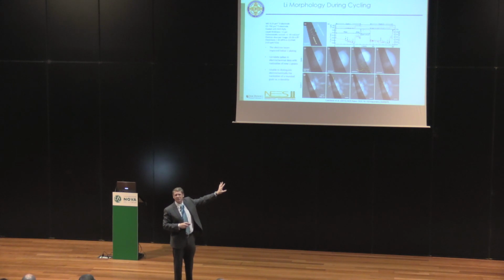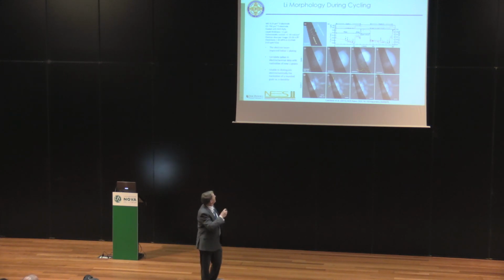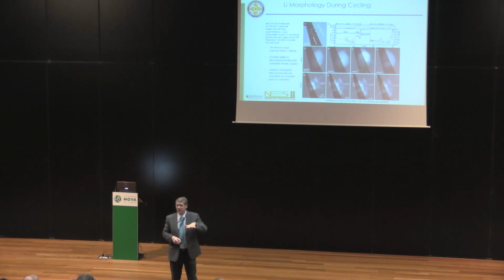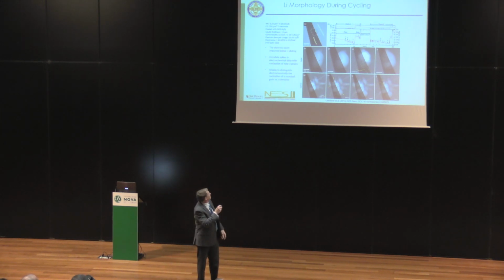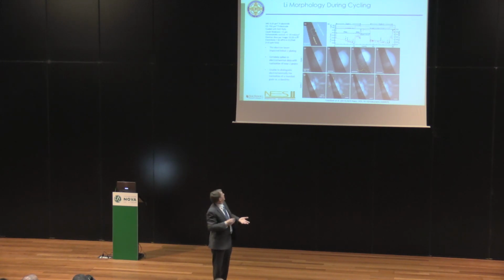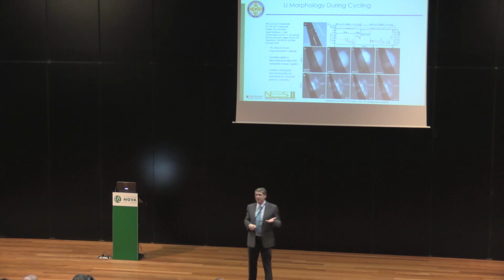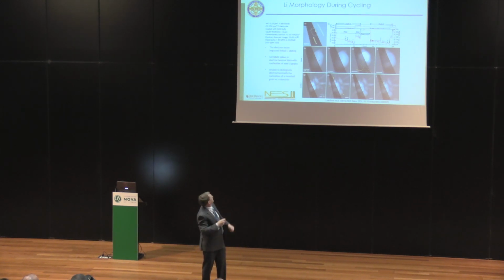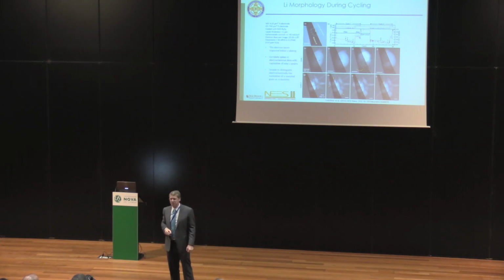Sticking with this case of a lithium battery, this is one of those fingers that we looked at earlier. This is a little bit bigger, a 500 nanometer electrical contact. This is looking in plan view. The entire surface was covered with ALD aluminum oxide. Then a small window was opened up, a 500 by 500-ish window within that oxide layer, and then a titanium contact was deposited. Then this was filled with a mixture of ethylene carbonate and DMC electrolyte, and then the lithium was deposited. You can see it's about 10 milliamps per square centimeter, so a mid-range current in terms of the deposition rate.